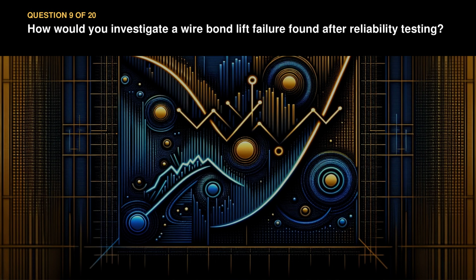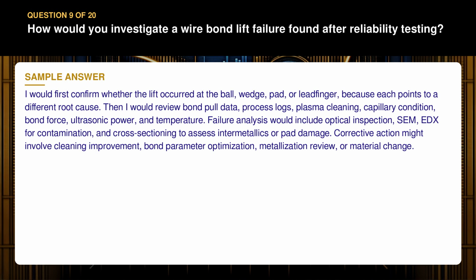Question 9. How would you investigate a wire bond lift failure found after reliability testing? I would first confirm whether the lift occurred at the ball, wedge, pad, or lead finger, because each points to a different root cause. Then I would review bond pull data, process logs, plasma cleaning, capillary condition, bond force, ultrasonic power, and temperature. Failure analysis would include optical inspection, SEM, EDX for contamination, and cross-sectioning to assess intermetallics or pad damage. Corrective action might involve cleaning improvement, bond parameter optimization, metallization review, or material change.